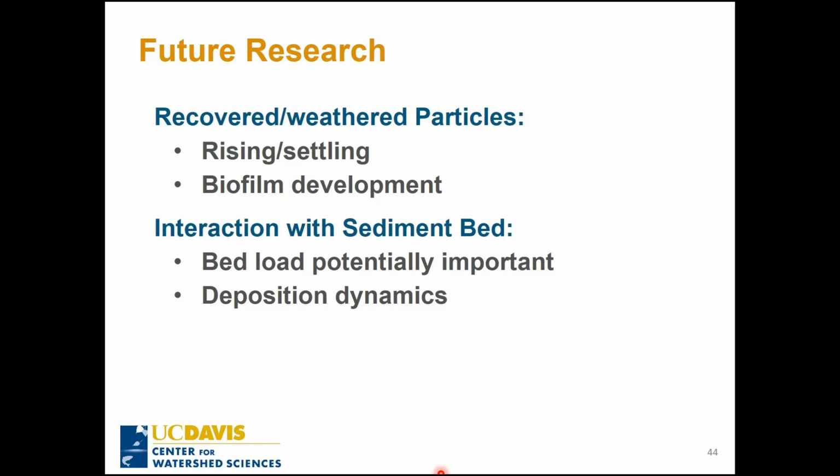So we can see it's really important to understand this kind of rising and settling differentiation between particles. And there's some additional aspects that we were not able to get into related to the development of biofilms and how that can alter that characteristic of the particles. Most of the research that's been done so far on establishing these rates has really used virgin plastics, often in the lab or in very controlled circumstances. And so I think there's a lot to be done using weathered particles, and in particular, particles that have been recovered through field sampling methods to get a better, more realistic idea of rising and settling in biofilm development.